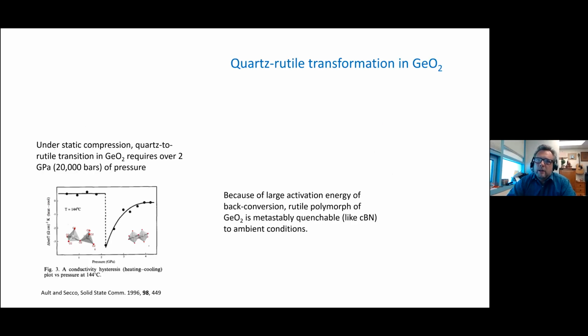So from diamond anvil cell experiments under ambient temperature, it was established that a pressure of about 2 gigapascals is needed for this transformation. This was measured in a paper published by Ault and Secco some pretty long time ago, where electrical conductivity was measured, and it was actually performed at 144 degrees Celsius. And they found that about 2 gigapascals of pressure were needed to induce this transformation.